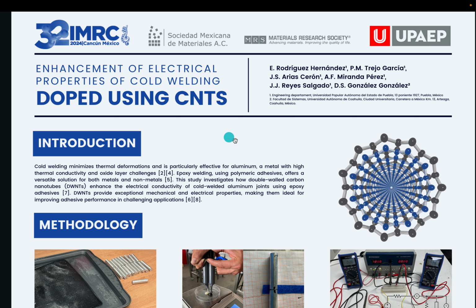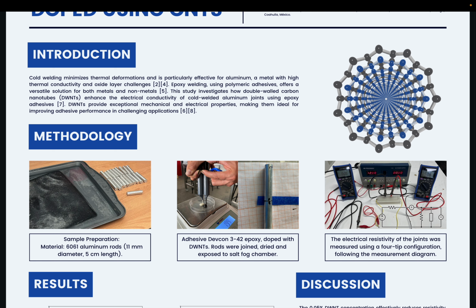For this study, we prepared a total of 40 samples using 6061 aluminum rods, which were cut into segments with a diameter of 11 millimeters and a length of 50 millimeters. The rods were then polished to ensure a uniform surface. We joined these rods using an epoxy adhesive, specifically the Devcon 3-42, which we doped with the double-walled carbon nanotubes at different volumetric concentrations, being 0%, 0.01%, 0.03%, 0.05%, and 0.1%.